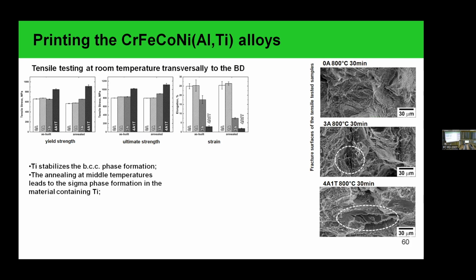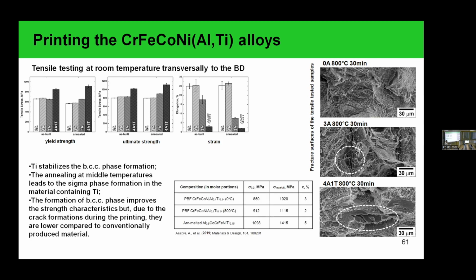Analysis of the fracture surface of our samples demonstrated the brittle zone, which is associated with the brittle BCC phases. Also, for the materials with titanium, we observed hot tearing in the as-built material. Comparing our results with earlier published work, which presented the mechanical characteristics for the arc melted composition with approximately the same chemical composition, we see that